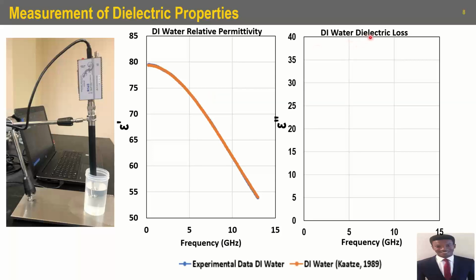measurements. On this particular chart, we see the relationship between the relative permittivity and frequency for deionized water. We pretty much see that the experimental data closely agrees with literature published values of DI water, which shows that our measuring tool is working appropriately. We also look at the dielectric loss as a function of frequency, and we see that our experimental data pretty much agrees with our literature published data.